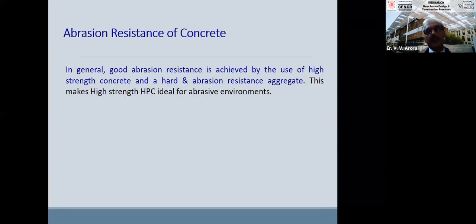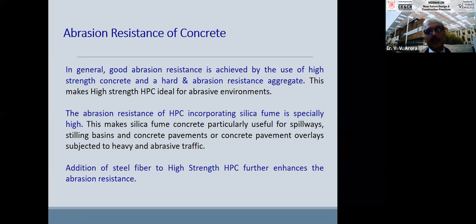Similarly, abrasion resistance I have discussed. Silica fume is particularly useful for spillways, stilling basins, concrete pavements, and concrete pavement overlays. Addition of silica fume has been found to give a higher resistance to abrasion. Similarly, steel fibers have been proved to enhance the performance in terms of abrasion resistance.